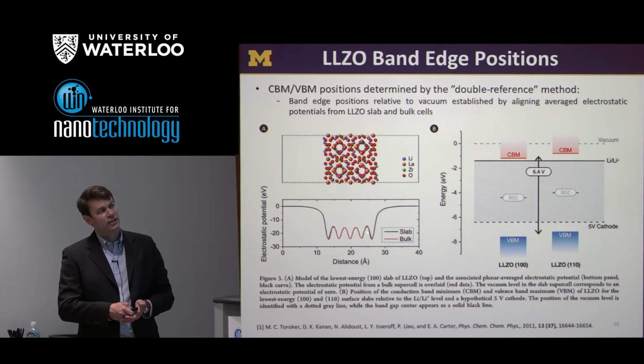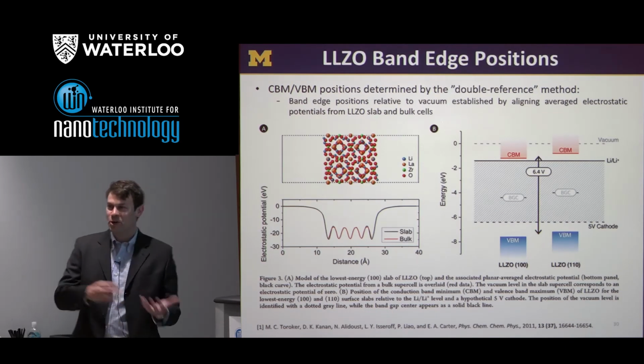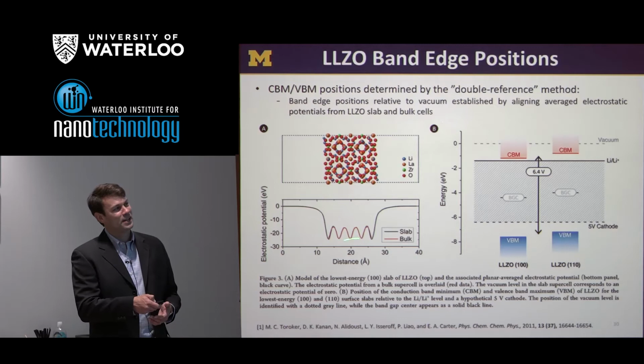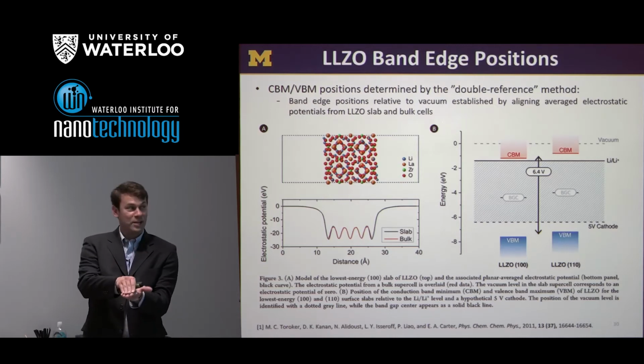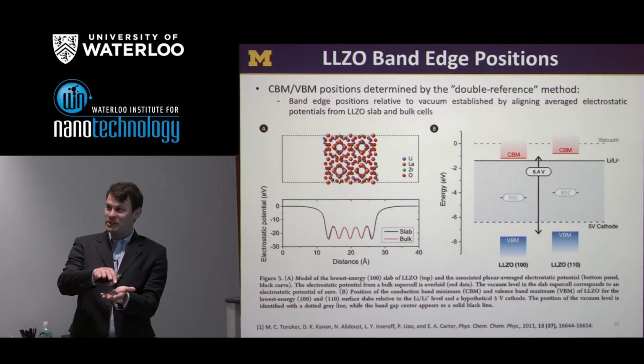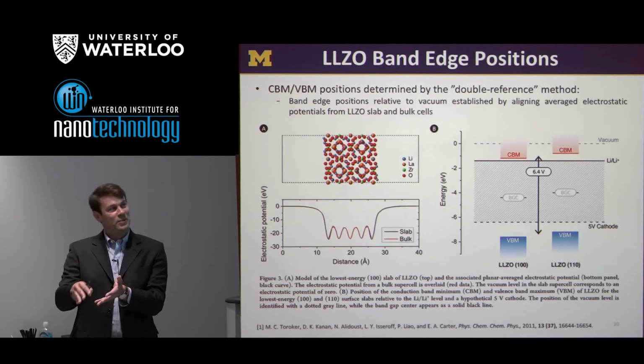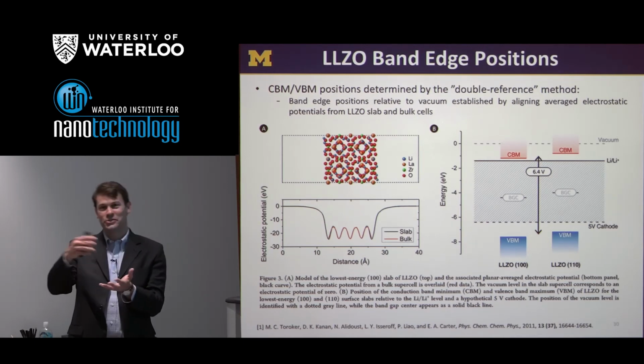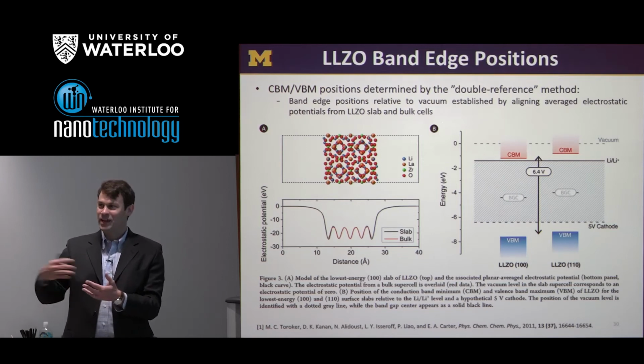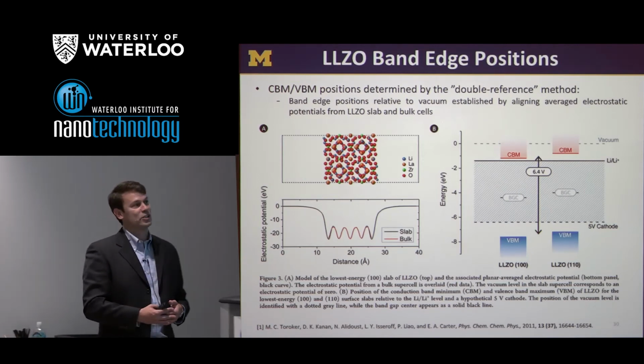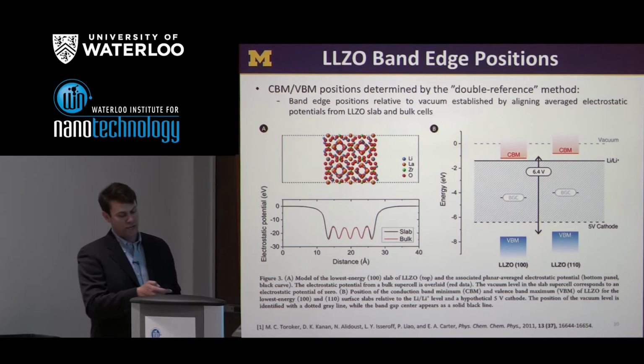And based on the electrostatic potential of that slab, so if you follow the black line here, this is the average electrostatic potential as a function of position across that cell, we can get an estimate of the vacuum level. And then by doing an equivalent calculation on bulk LLZO, this is the red line, we can align those electrostatic potentials, and in so doing also align the band edge position. So it's basically aligning electrostatic potentials, which are relative to the vacuum level, and there's a second reference there to what's happening in the bulk with respect to these band edges.